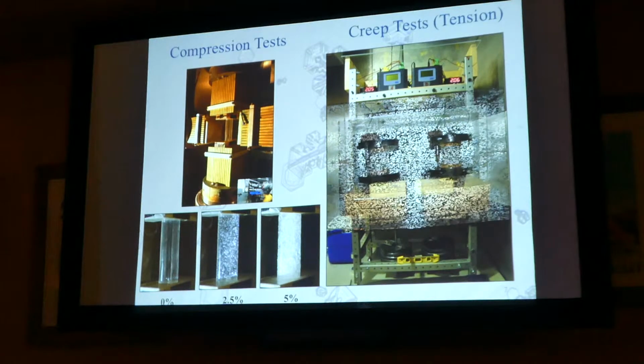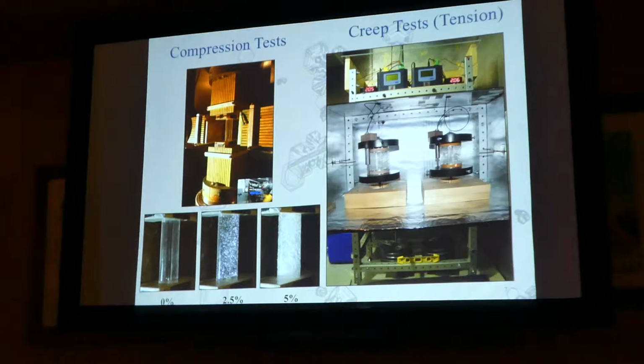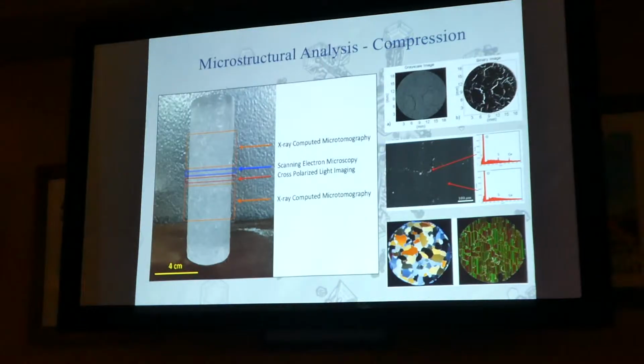And then also over here, we made this jig where we would stretch. We would put weights, you can see weights hanging down here on these dog bone pieces, and we let that weight sit there at a constant temperature for sometimes weeks, like up to 8-9 weeks or so. And we'd see how the ice actually stretched over time. And then, of course, one of these samples would be doped with sulfuric acid, like 10 parts per million, so just a very tiny amount. And then one would be just pure water, so to serve as our control in our comparison. And so what we'll look at is how those two compared to one another.